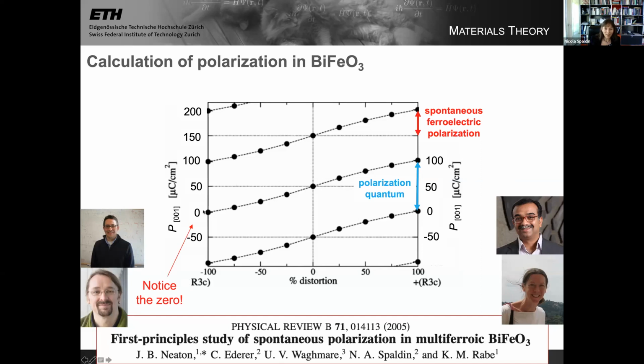The first is this 0 here, and also over here. And this is an allowed value for the polarization of the fully ferroelectric structure, if it's in one orientation or another. The allowed values of the polarization are 100, 200, and so on. The spontaneous polarization is 100 minus 50, it's about 50 microcoulombs per square centimeter. But one of the allowed values is 0.